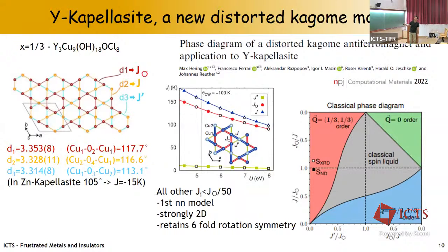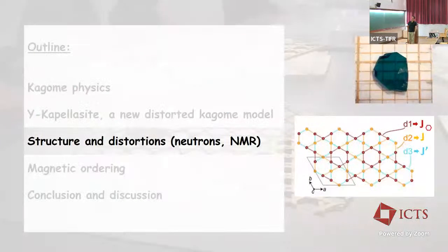And interestingly, at the center you have the isotropic Kagome point, and you have also an extended regime where you have a so-called classical spin liquid, which to me is still a bit mysterious, but there are states where there is a large degeneracy of the ground state, but it's a discrete degeneracy. So these ground states are not connected as what I was showing for the pure Kagome case. It could be called jammed spin liquid in relation to previous studies.